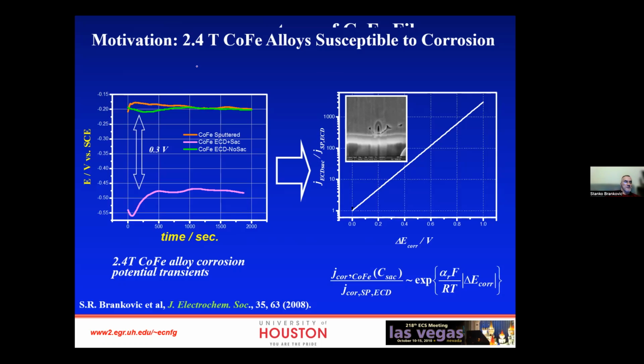If the film is supposed to go through cycles of thermal treatment, then you need to be worried about the stress in the film. But if the film also needs corrosion resistance, low stress, and good magnetic properties, then you have a trilemma that you need to solve.